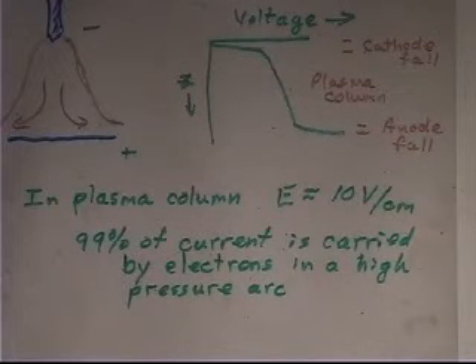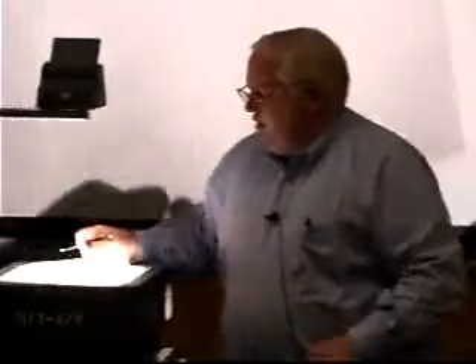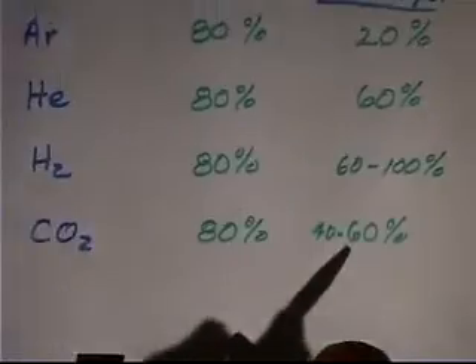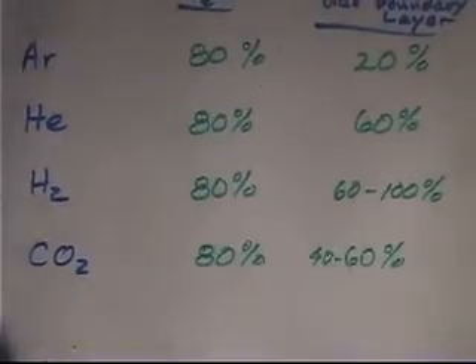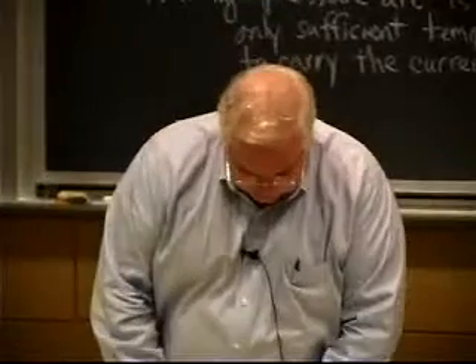And if you look at a plot, which I didn't bring, of thermal conductivity as a function of temperature, there's a peak at around 3,000 Kelvin, because above 3,000 Kelvin, the gas is absorbing heat by dissociating the polyatomic molecules. At 3,000 and below, they recombine, and below 3,000 they're just molecules, so there's no reactive thermal conductivity. But this rejoining of the molecules in the boundary layer actually enhances the heat transfer with polyatomic shielding gases. So when you go out there in the real world, you'll find that welders use all kinds of different gases, and virtually nobody in the welding community has the foggiest idea of why one gas transfers heat differently than another. Although, frankly, the physicists and the chemists understand, but they would never talk to a welder, so what difference does it make? Right?